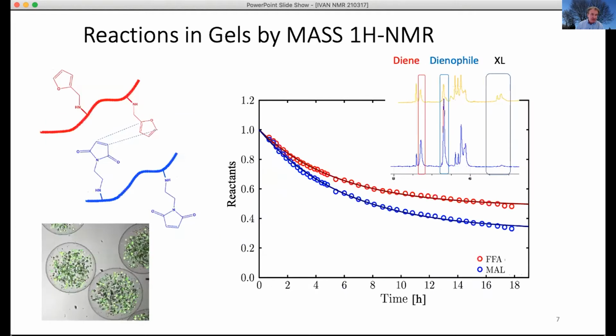So we can apply this, and I'm just showing a few sample spectra. The most important point we learned from this technique is that as the polymer reacts, not only do we have cross-linking that drops our two reagents, the imide reacts faster because it also hydrolyzes in a side reaction that's relevant to our scale. This allows us to get chemical insight into the formation of these gels.